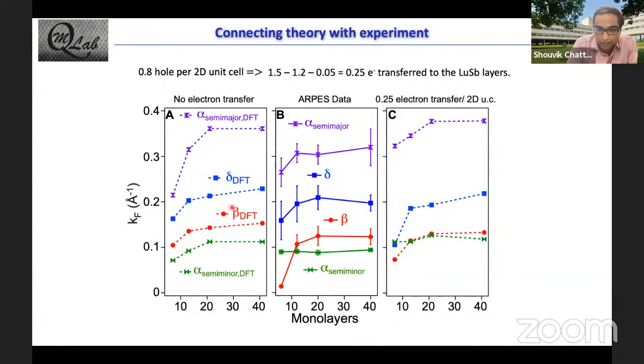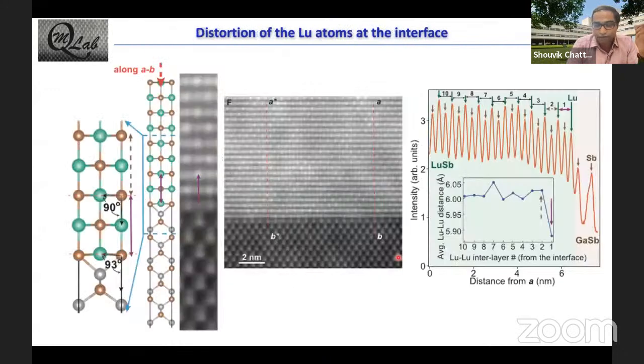So this was without electron transfer, and this is with 0.25 electron transfer, and you can see that we have quite a good correspondence. Now we can take it one step further to give further support that what we are claiming here is actually true. In an ideal rock salt structure, if you calculate this angle between the lutetium, antimony, and lutetium, it will be 90 degrees. But at the interface, because there is a bonding mismatch, there is actually a distortion of the lutetium atoms, which gives you a little distorted angle of about 93 degrees.